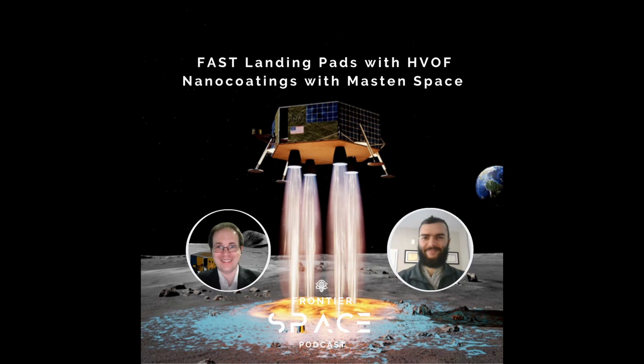I mentioned that the conditions on the moon are a little different than Earth because there's no atmosphere. So your rocket plume tends to spread out, and that really helps us out from a stress perspective. You get a really broad plume impinging on the surface relative to Earth, where instead of, say, a meter on the moon, on Earth you get about 3 centimeters of impingement diameter for that core plume. So you can spread that load out over an absolutely huge area.